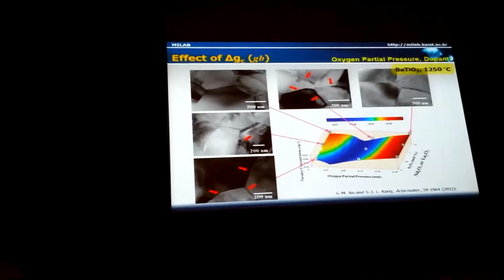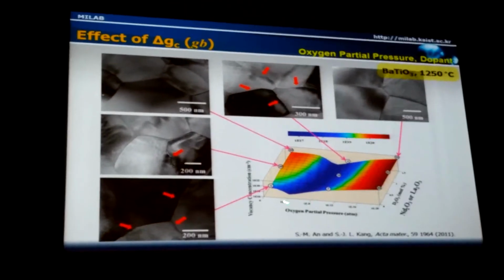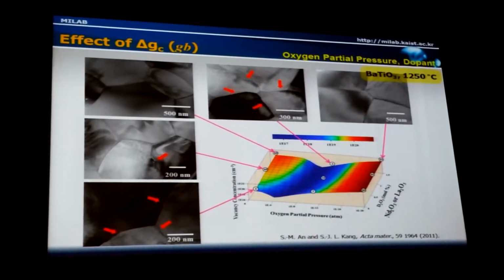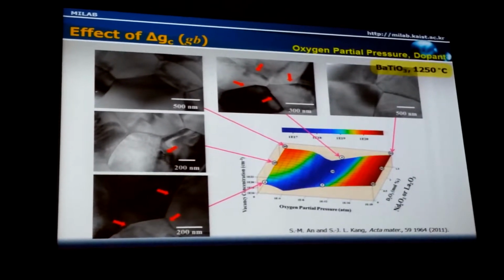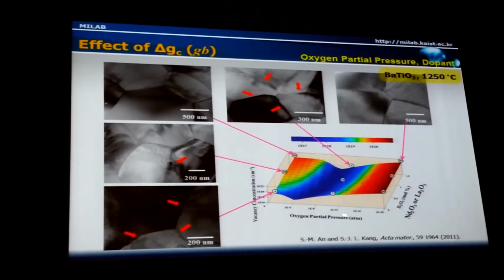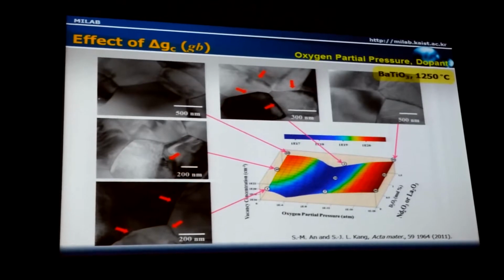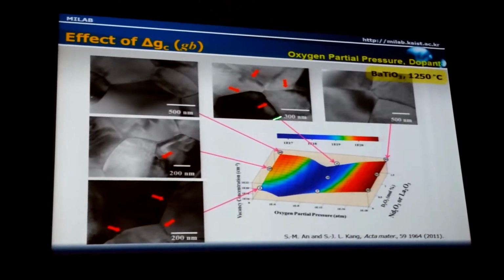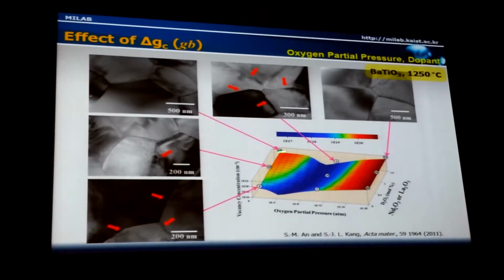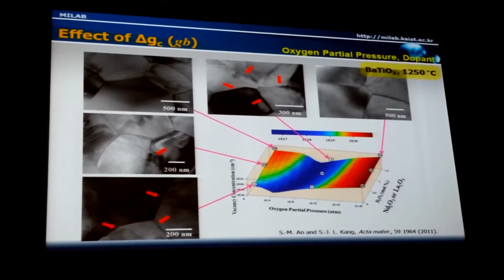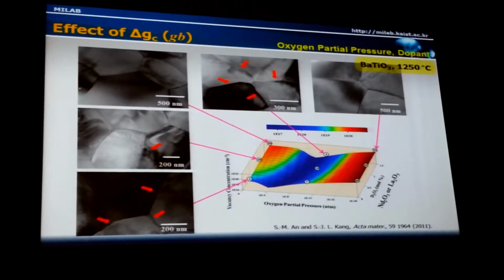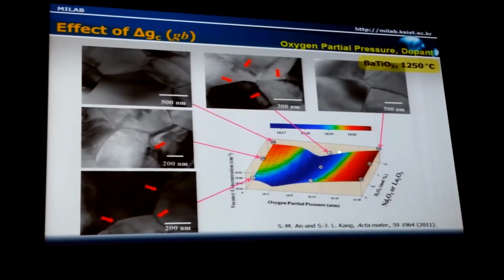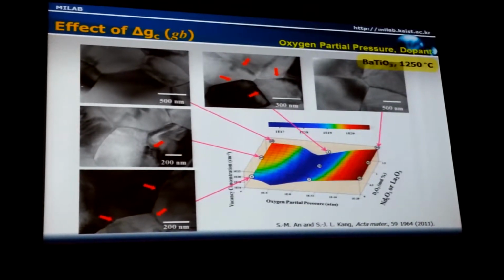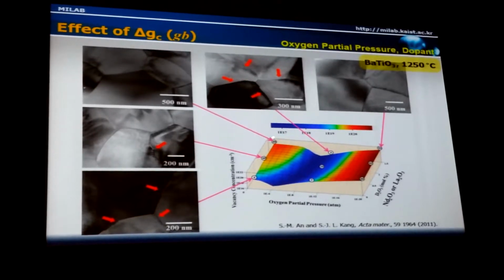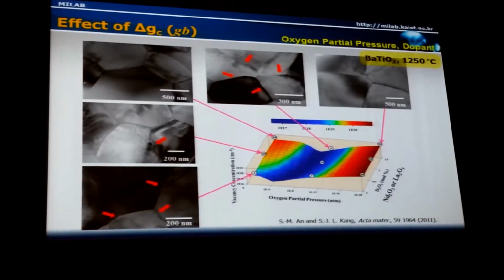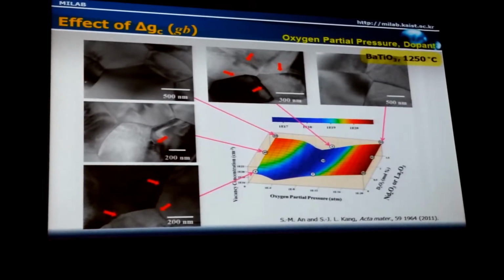This is the estimated variation of the total vacancy concentration as functions of oxygen partial pressure and donor dopant concentration. Depending on the donor dopant concentration and oxygen partial pressure, the grain boundary structure changes, rounded or faceted. The numbers in circles show the fraction of disordered, rounded boundaries. When the total vacancy concentration is low, the grain boundary is well faceted. When the total vacancy concentration is high, the grain boundary is smoothly rounded.